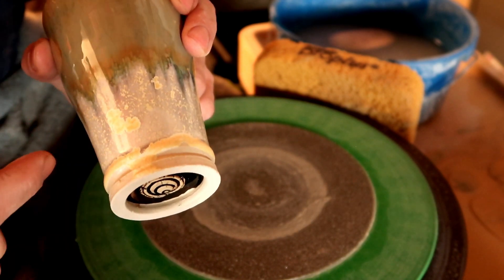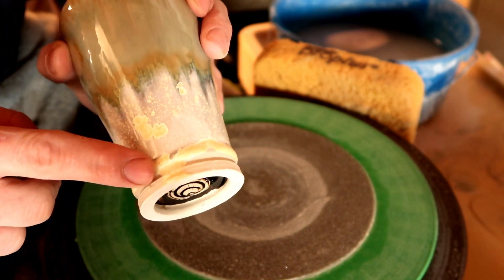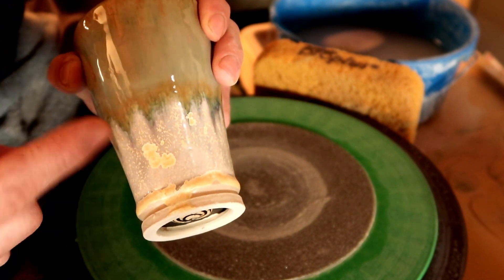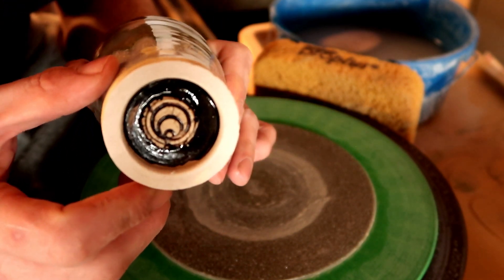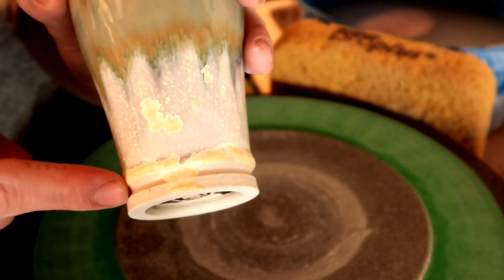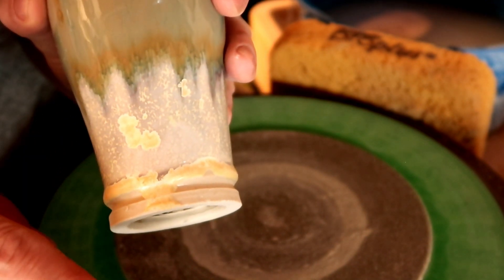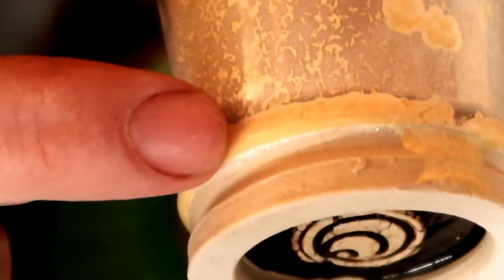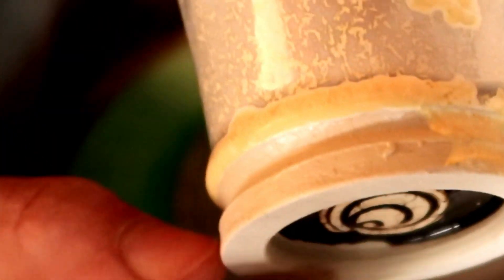It's very versatile, and usually by this point, whenever I'm throwing a pot, I know I'm going to put crystal glaze on this one, so I'm probably going to put a glaze line on these five pots. Next time I glaze, I know these ones have the glaze line, therefore they get the runnier glazes. This prevents me from having to do all of this work in the first place, leaving me with a nice clean foot. Granted, this isn't a 100% guarantee — it doesn't make it so that you'll never have runny glaze again. But it does help a little bit. If you look really closely, you can see where the glaze bunched up and tried to muster up the courage to go over that line, but couldn't do it.